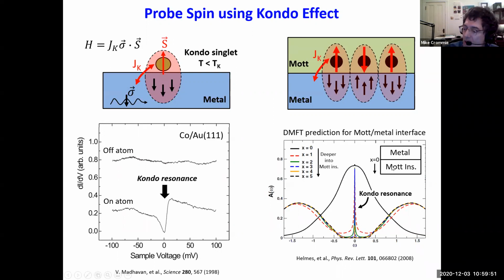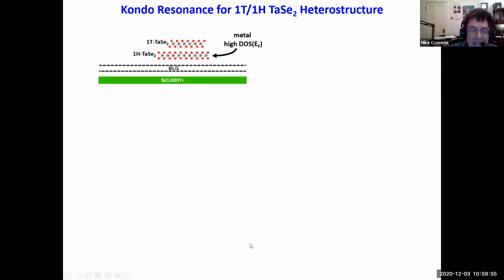And then if you go deeper into the Mott insulator, then you just get the Mott gap. So that's a prediction. And so we decided to use this technique to see if we have local moments in our Mott insulator. So we put our material, which we believe is a Mott insulator, 1T TaSe2, onto 1H TaSe2, which is a good metal.